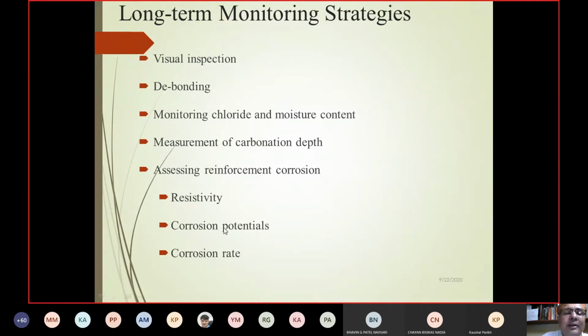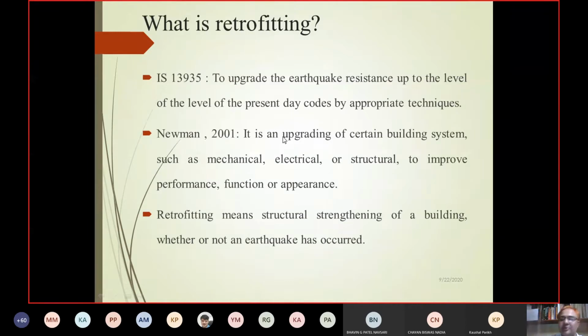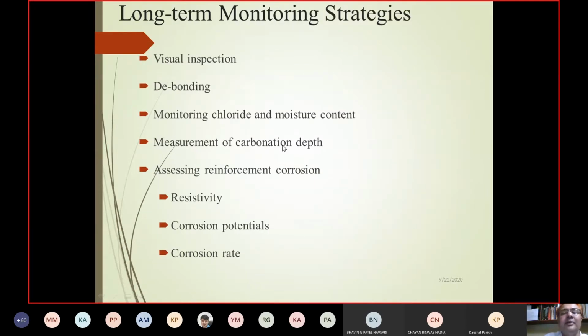Half-cell potential meter and all the things we are using to test the corrosion rate, corrosion potential, resistivity, and check the carbonation rate by phenolphthalein. In simple terms, you can drill the surface of the RCC, every 10 mm drill, collect the dust in various plates, and put phenolphthalein on that. The first 10 mm is fine, second 10 mm, third 10 mm or 5 mm, you can know the carbonation rate by that. In industry, this is a good practice. What I mean is that in residential buildings also this practice should be welcome.